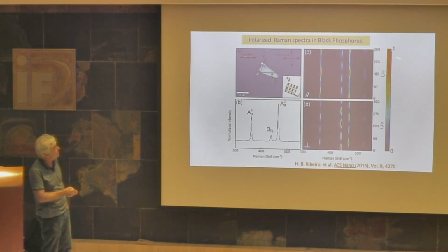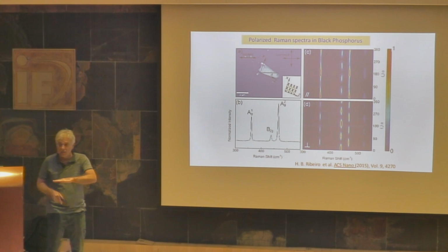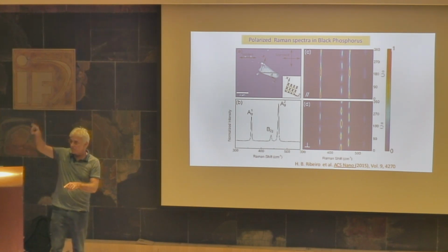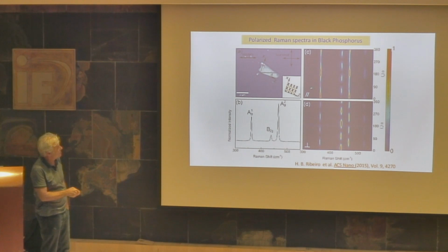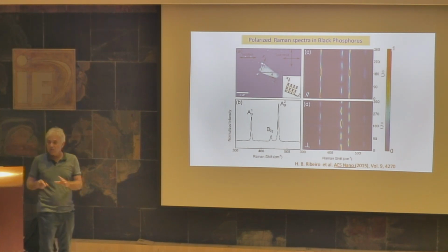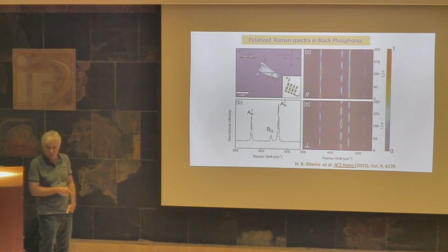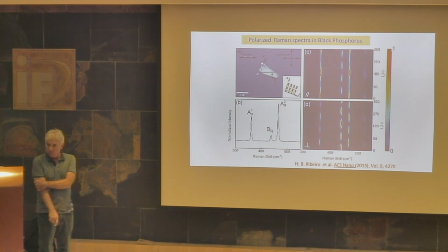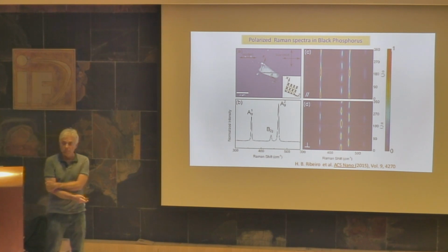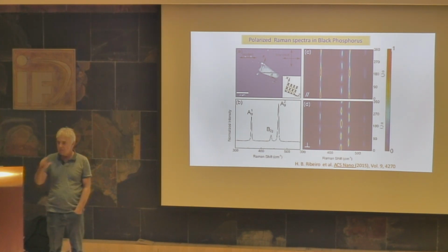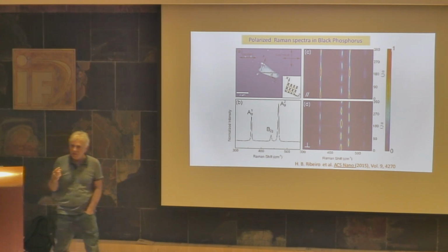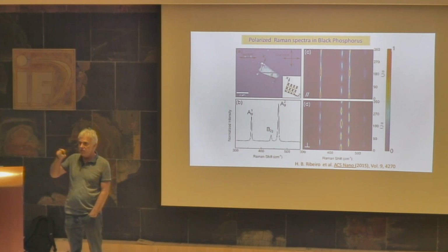This is, for example, the parallel configuration, and this is the crossed configuration, and I'm rotating the sample from 0 to 330. Then you see the intensity of the peaks becomes strong and weak, okay? This is the parallel and the crossed. In order to get the Raman tensor, you need to do those two experiments, fit the data, and then you get the Raman tensor. We also have a new paper that just appeared in PRB, with germanium selenide. And now I have one student studying a more complicated system, rhenium disulfide, because rhenium is triclinic, another symmetry.